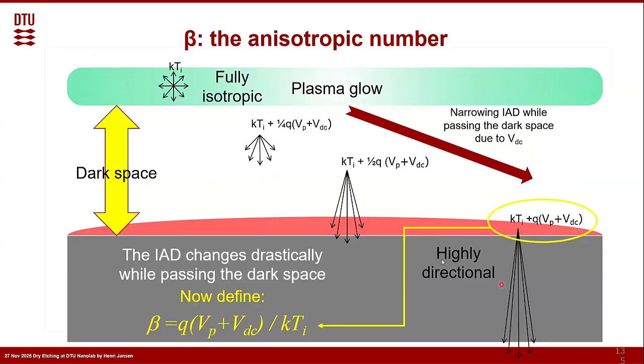So our ion angular distribution has been sharpened. Here it is very broad, and it's getting sharper and sharper, where here is the maximum. Now we can define this directional part with respect to the isotropic random temperature of the original ion temperature in the plasma. That's beta. Beta is the elemental charge of the ion times the plasma potential plus the DC bias, that's the bias gained in this dark space, divided by this isotropic one.